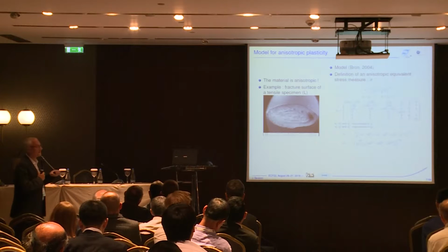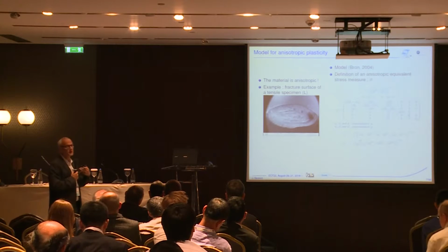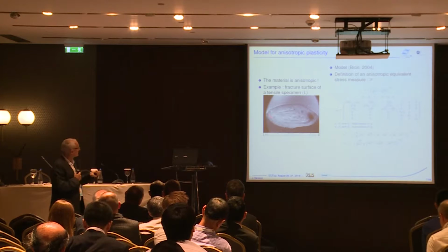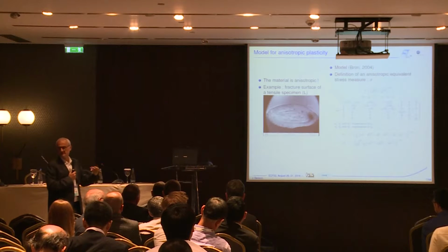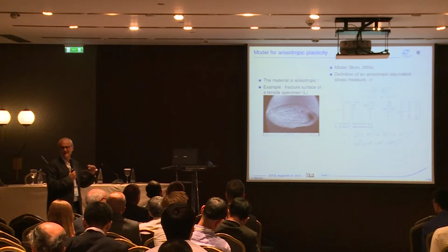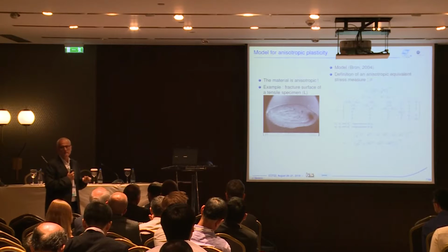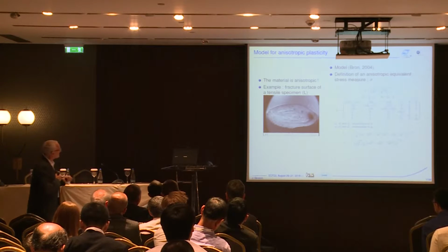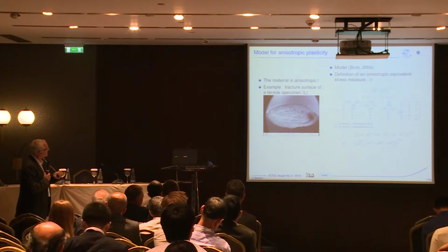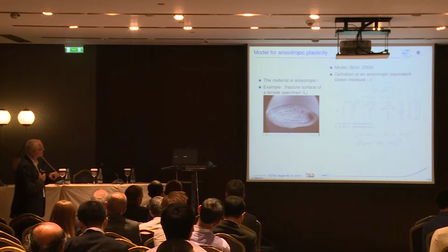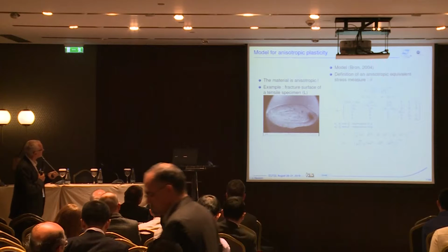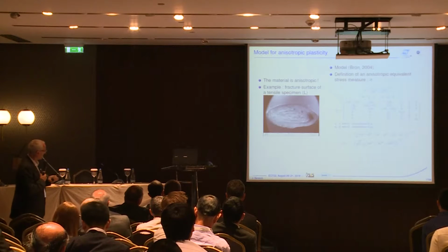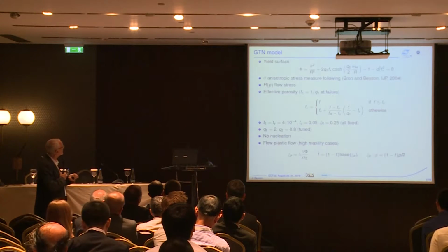And I really think it's no use trying to apply any damage model with such a level of plastic anisotropy if you don't attempt to model that. Because the stress field that you may use, neglecting plastic anisotropy, may be very wrong. So here, in this work, we use the model we developed quite a long time ago now. It was initially developed on aluminium, but we use it also to represent the behavior of such plate materials.